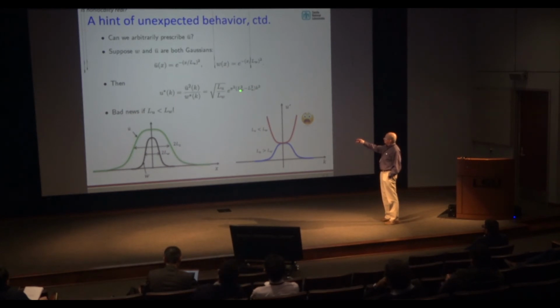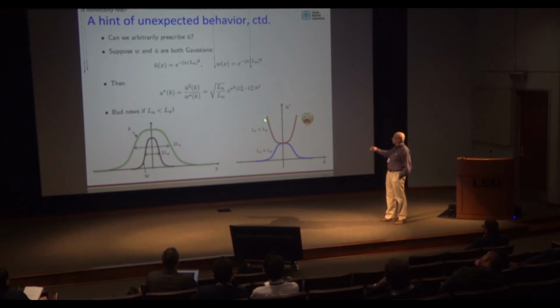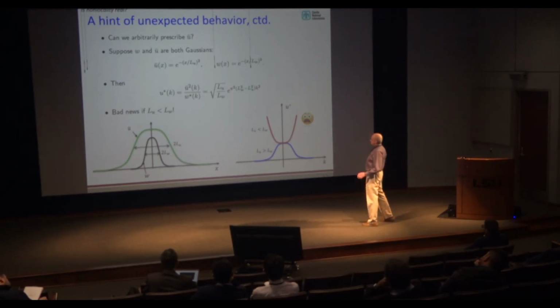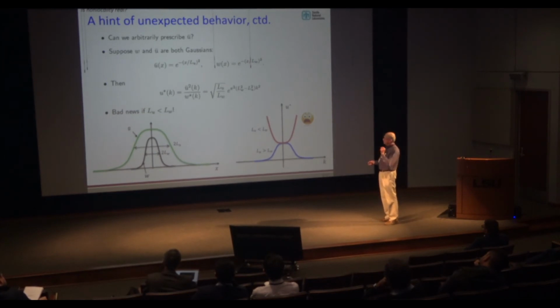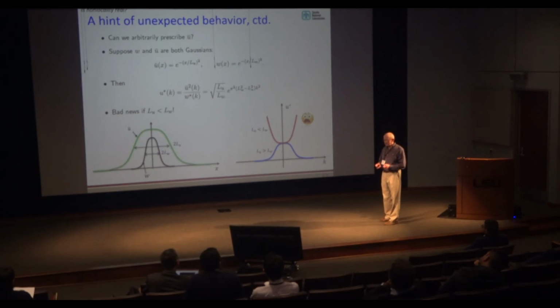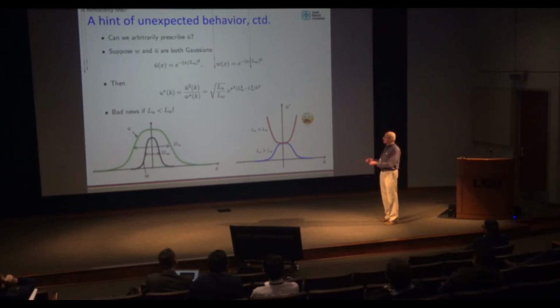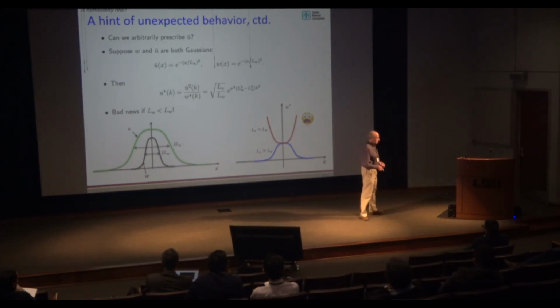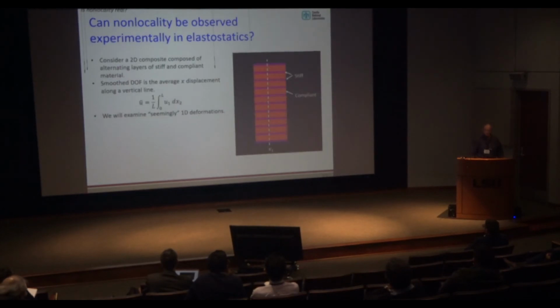So if this exponent is negative, we're in good shape. It's just this Gaussian. But if it's positive, then we're in trouble because the Fourier transform of the small scale displacements blows up for large wave numbers, and you can't do the inversion of the transform. So what that means is that if your prescribed smooth displacements have more high frequency content than the smoothing function, you can get into trouble because there might not be a small scale displacement field that generates what you assumed were the smooth displacements.